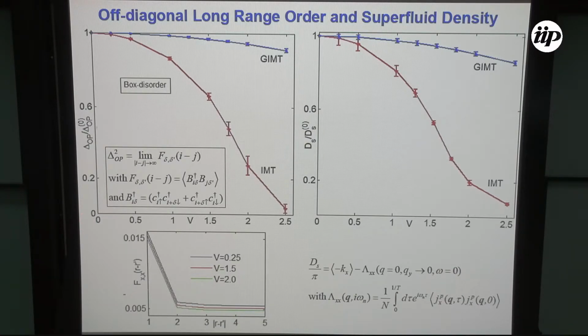In IMT, with no strong correlation, if you introduce disorder, this value goes down, and superconductivity is killed at around 2.5. Remarkably, if you introduce strong correlation in GIMT, you will see that it's quite robust to disorder. The value falls hardly 5 to 10%. It's so robust that you can also see in superfluid density that it behaves very similarly. IMT falls down, but GIMT doesn't.